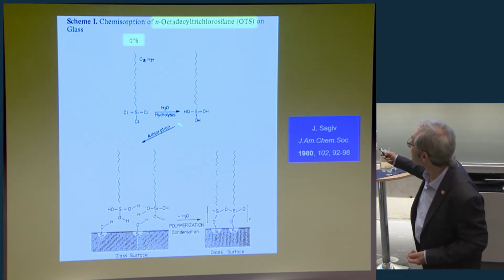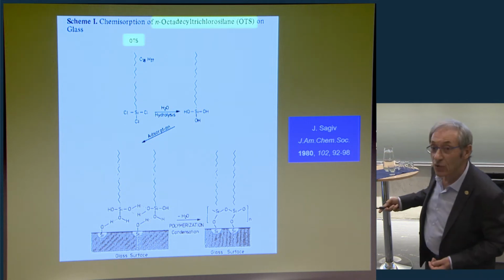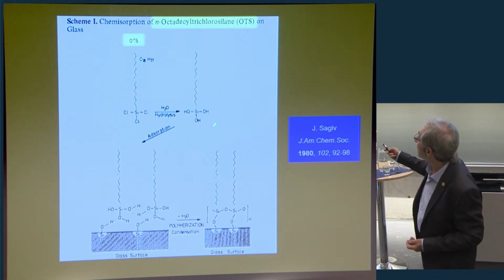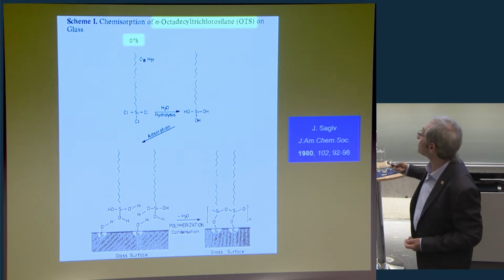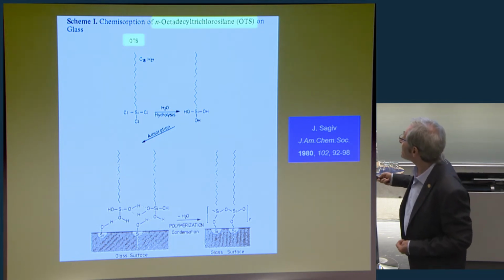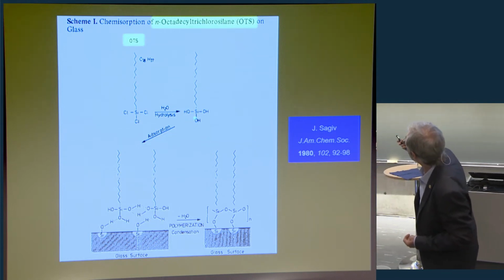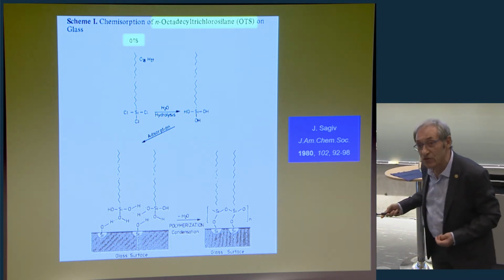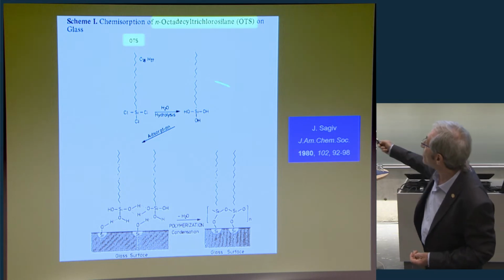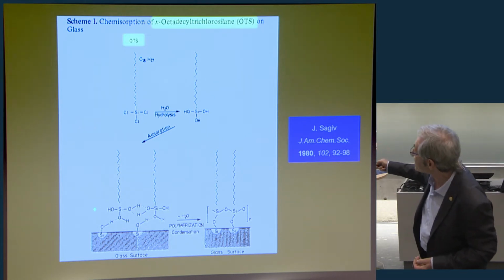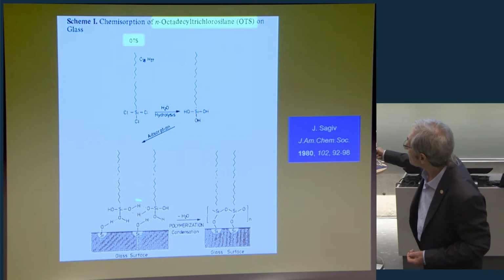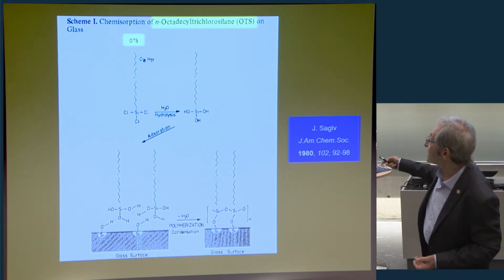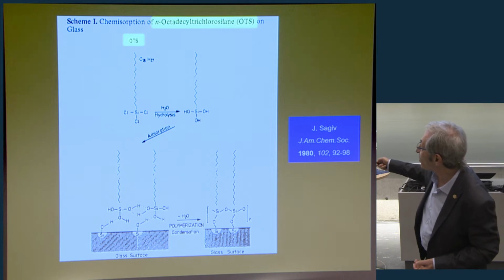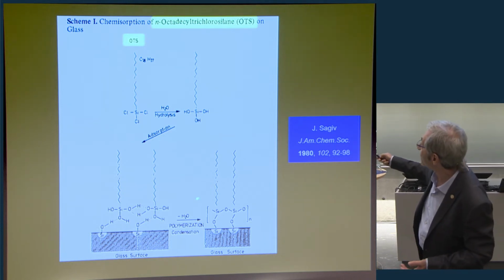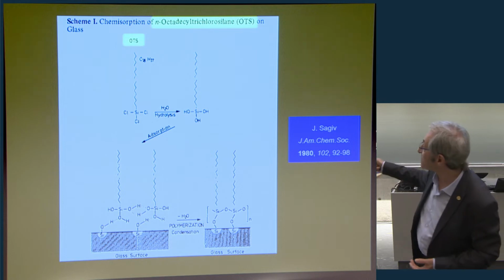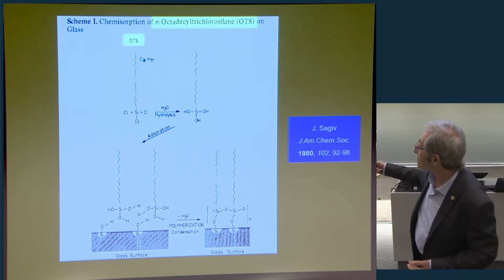But reacting with water, the chlorines are removed, and this is extremely water sensitive, and you obtain in situ the molecule in which the chlorine is replaced by hydroxyl groups, silanols. This molecule now can adsorb on surfaces and also can bind covalently by condensation reactions, where a molecule of water is liberated, and you may have silicon-O-silicon lateral bonds and silicon-O-silicon bonds to the surface.